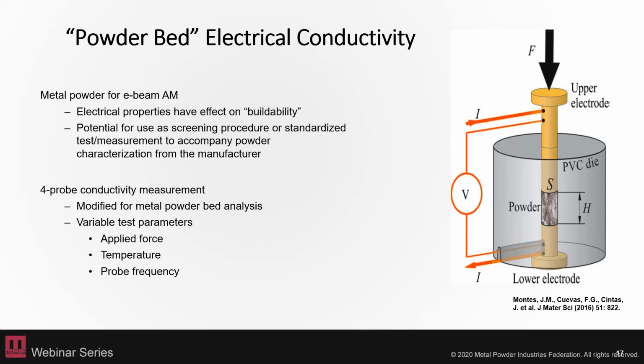This is based on a 4-probe conductivity measurement that's pretty common across the industry for conductivity, and then modified for a metal powder bed analysis that gives you some conductivity measurements. It's variable according to your force, your temperature, and your probe frequency, but you could develop a standardized test method for your particular workflow that would give you information that's critical to the process.